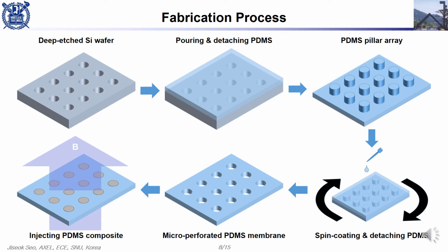This is the whole fabrication process of freestanding PDMS composite pressure sensor arrays. First, silicon wafer was etched with dry etching to obtain a mold and replicate those structures with PDMS. After peeling off PDMS pillar arrays from silicon mold, surface treatment was conducted to lower the adhesion force between pillar structures and PDMS through-hole membranes. After the treatment, PDMS prepolymer was spin coated and annealed to achieve micro-perforated structure. Finally, PDMS membrane was peeled off from the pillar structure and PDMS composite was injected into the whole arrays.